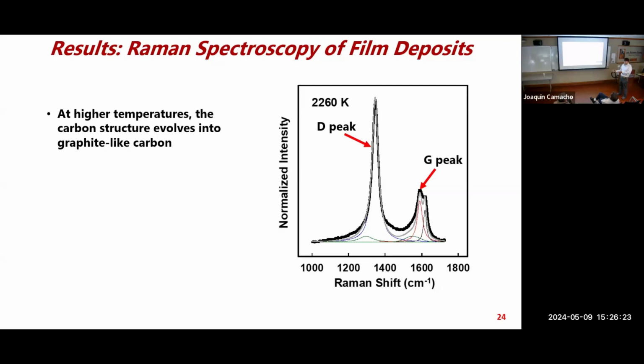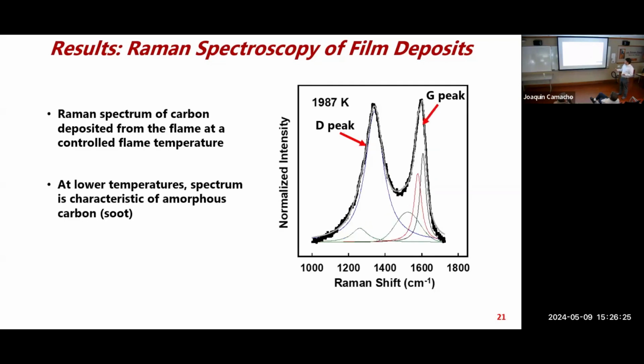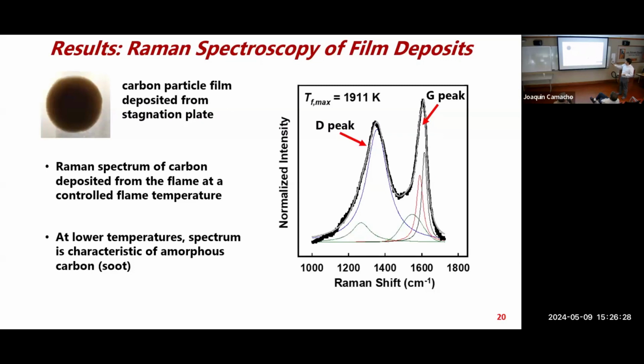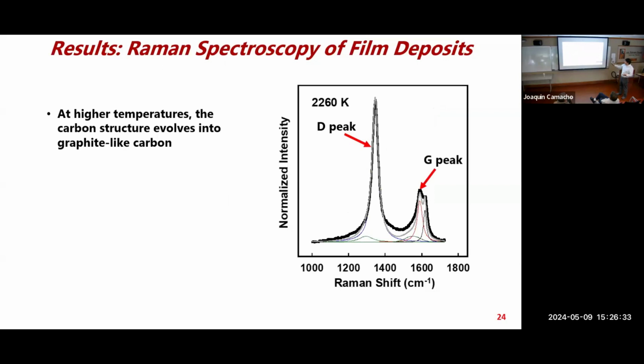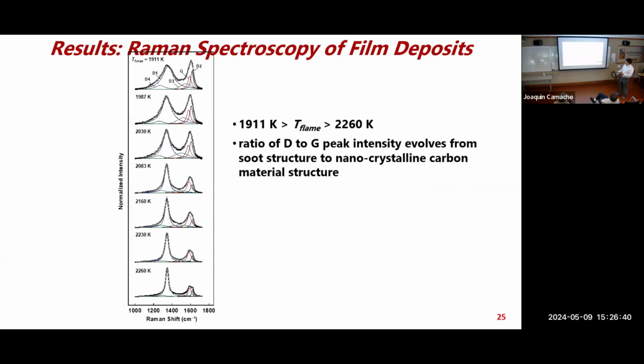the Raman spectrum. And this is the high temperature, clear evolution from typical flame temperatures, or more on the high end of flame temperatures, going to even higher. We do see that the film grown is much different than soot. That's a first evidence. And so yeah, this is the evolution. And again, you can do some analysis, and according to the literature, you can make a lot of inferences on the structure based on these peaks and things like that. And I have done that. I didn't put the reference here, but a few of my papers are looking at this analysis.